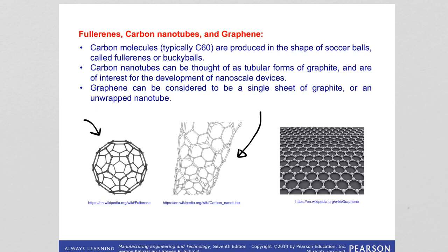Carbon nanotubes are very strong, okay? And usually they are used as fibers in composite materials. As of now, the difficulty is that these nanotubes tend to attach to each other, forming clusters, so it is very difficult to disperse them in the composite matrix, like a polymer matrix. If we cannot disperse them homogeneously throughout the structure, they are not effective reinforcement materials. They can be used in bicycle frames, baseball bats, golf clubs, tennis rackets. These reinforced composites can be used in these applications.